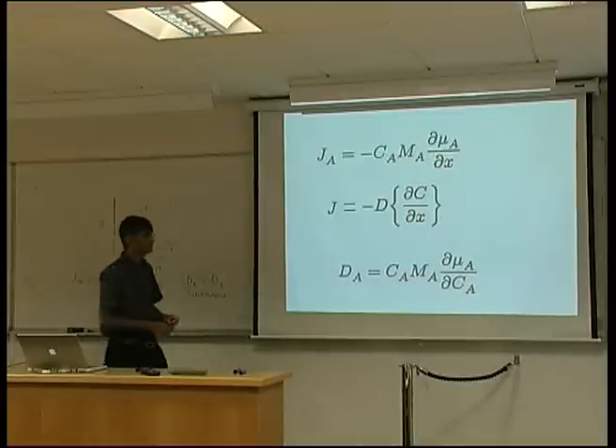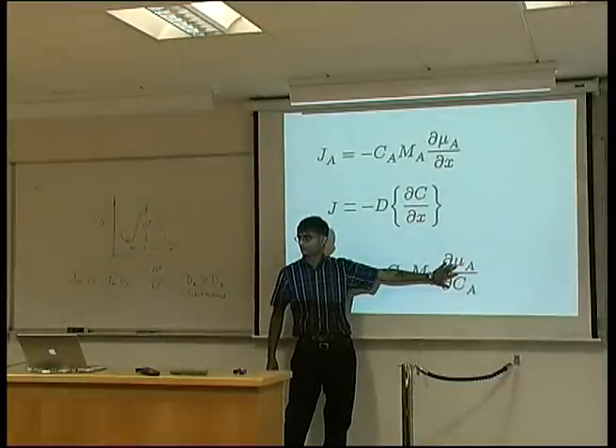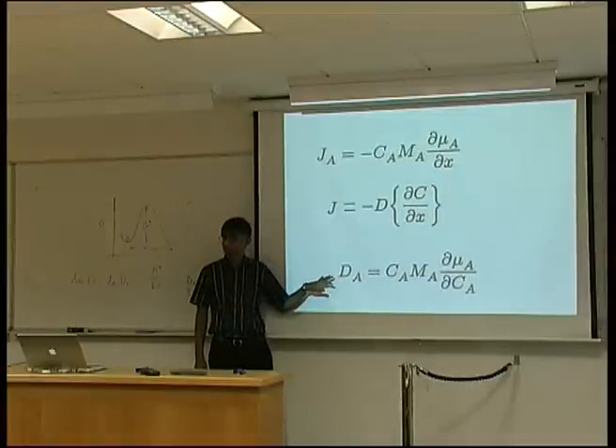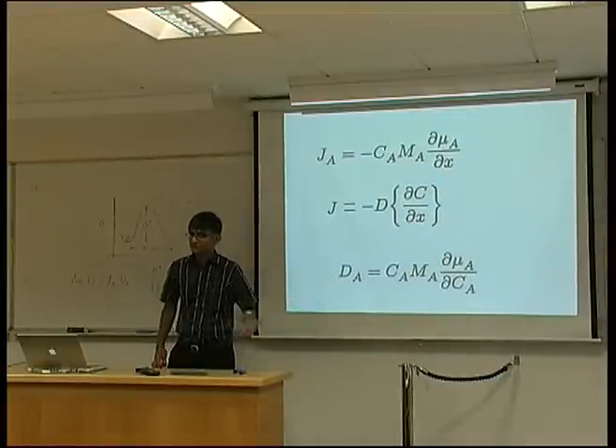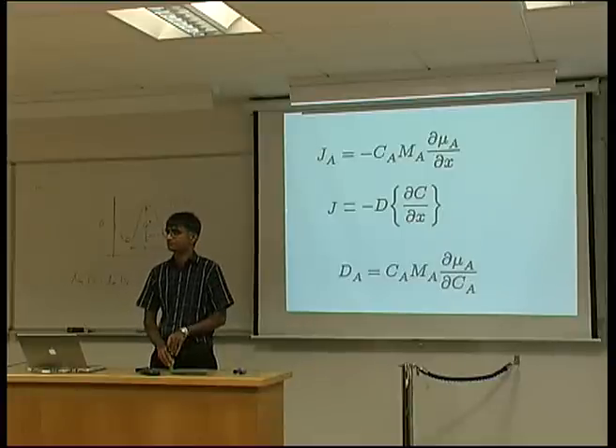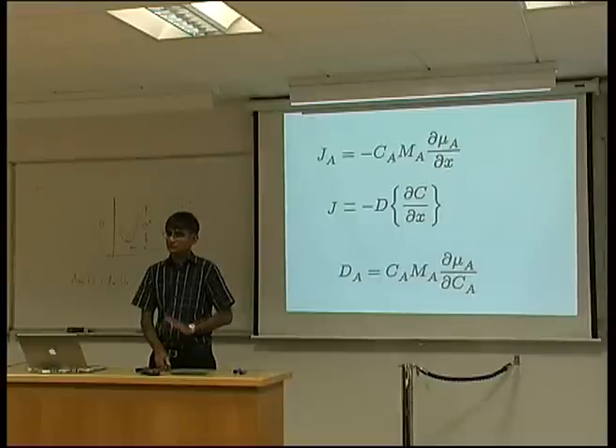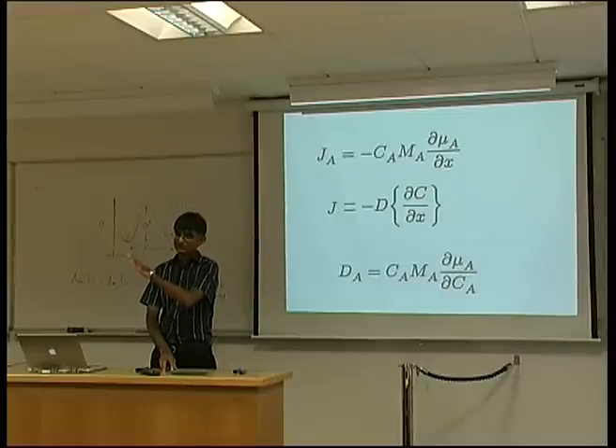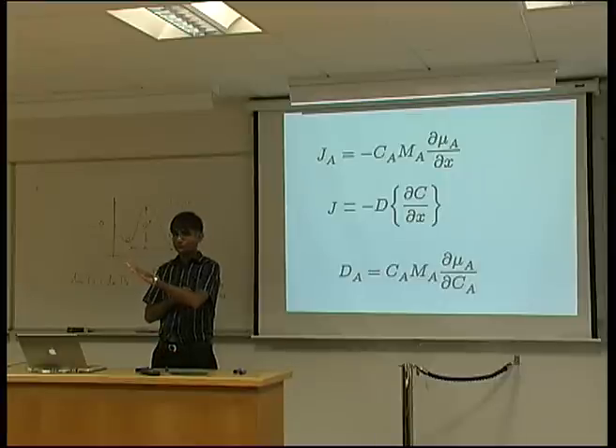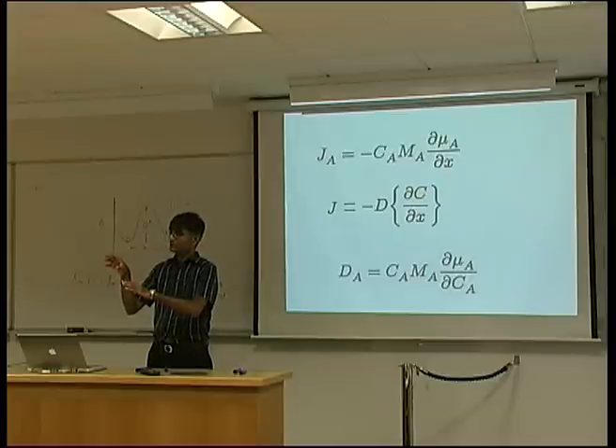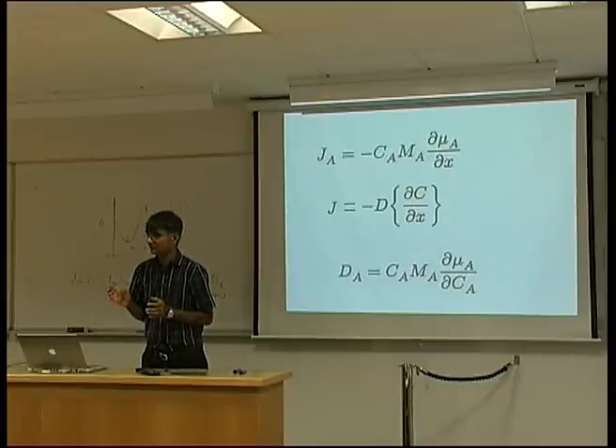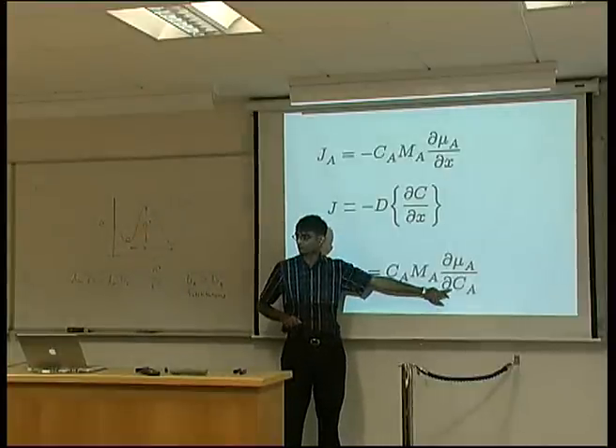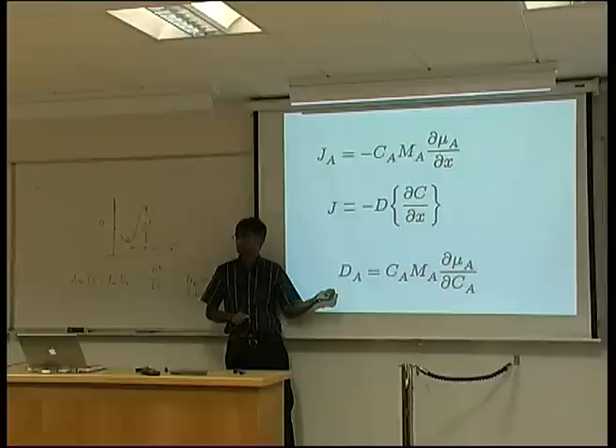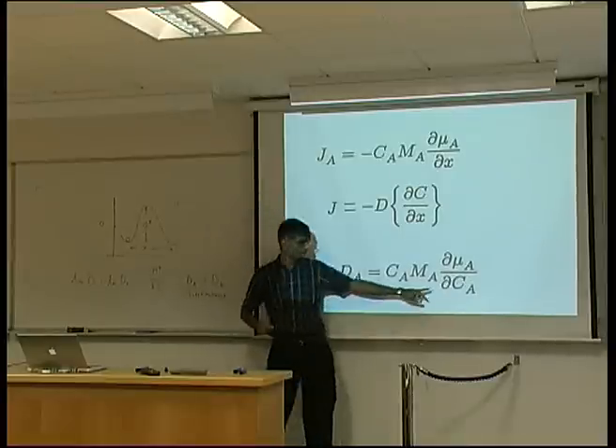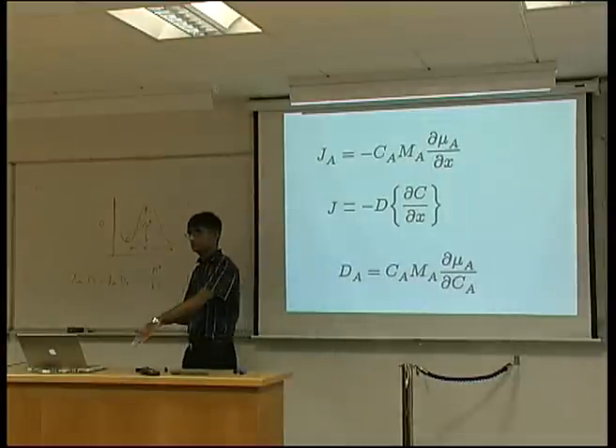In the next lecture, I'll show you that this can actually be negative, in which case the diffusion coefficient becomes negative. What does that mean, a negative diffusion coefficient? That means solute will climb up a concentration gradient. So you will go from solute poor regions to solute rich regions. So I'll show you circumstances where you get what's known as uphill diffusion. If this term is zero, the diffusion coefficient becomes zero. And it's only when this is positive that you get diffusion happening down a concentration gradient.